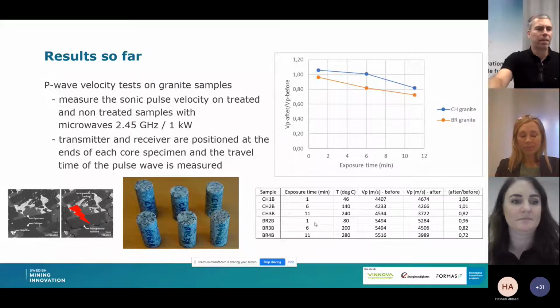So we started looking at the impact of microwaves on different rock samples. And the way to assess that is to use this method, which is called the P-wave velocity test, so that we apply ultrasounds on rock samples. And then we measure the sound velocity. So we have samples that are measured like that before treatment with microwaves and thereafter. And we take the ratio between the velocities.